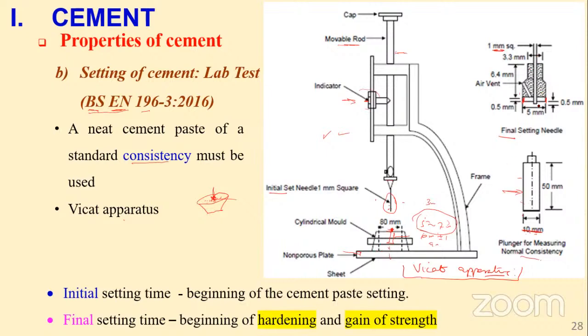The same thing for the setting time. There is a 10 millimeter, a 5 millimeter gap and a 5 millimeter, so the penetration from here to the end here is 1 millimeter. And then it rests on the surface. When you release it for the final setting time, this exposed part of the needle will penetrate, but these sharp edges here just make a mark on the outside. So if we talk on plan, there is a penetration of the needle and the attachment. The hollowed out metallic attachment, this part, just makes a mark.